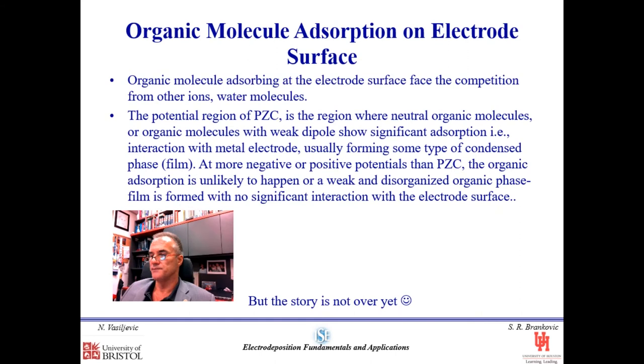So, a typical rule is that additives are generally larger molecules which have a small dipole, and they can only effectively compete for an adsorption site on the surface when the probability of disorder in the interface is maximized by the fact that we are close to the potential of zero charge. Then they can actually effectively compete with water molecules or metal or other positively or negatively charged species and adsorb on the surface.